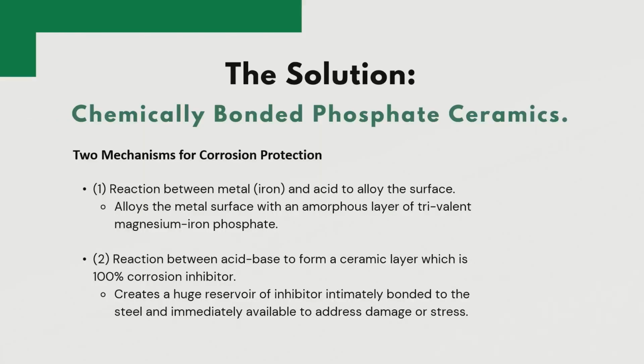All right, so how do we solve the problem? What we try to do is react the metal with an acid to alloy the substrate. We create a protective layer on the coating by giving the steel something to react with other than oxygen. I'll get more into that in just a second. This reaction between the acid and the base forms a protective layer. And this protective layer is essentially an alloy. It prevents voltage from crossing the substrate and prevents corrosion because it's an inert layer.